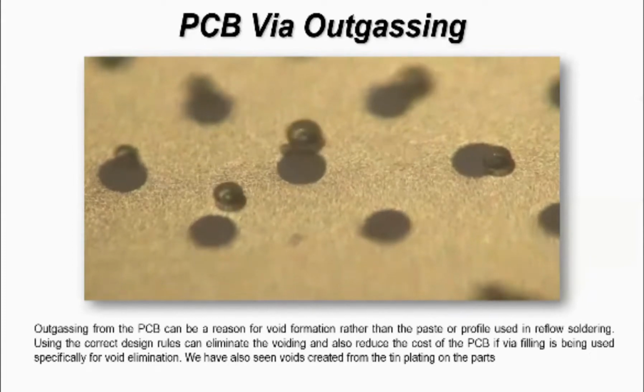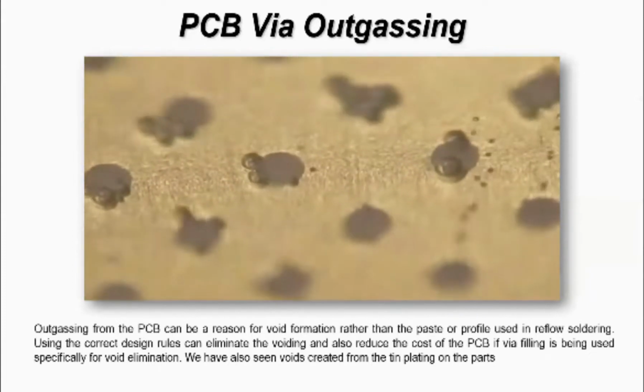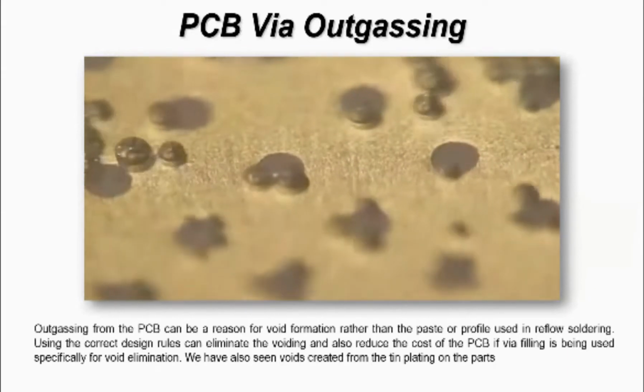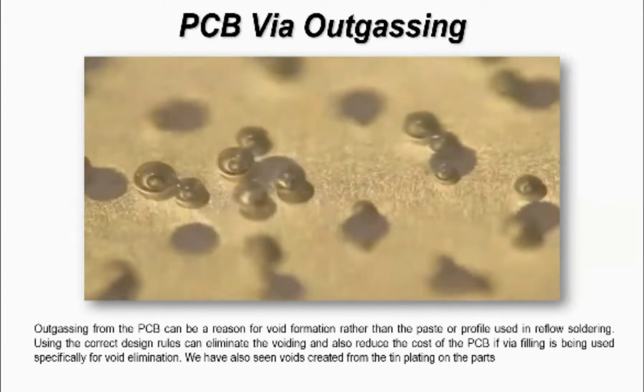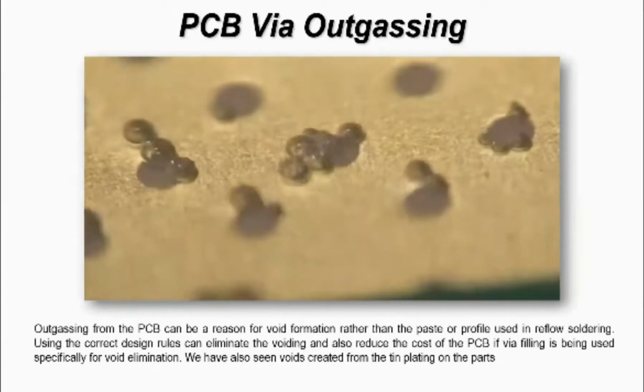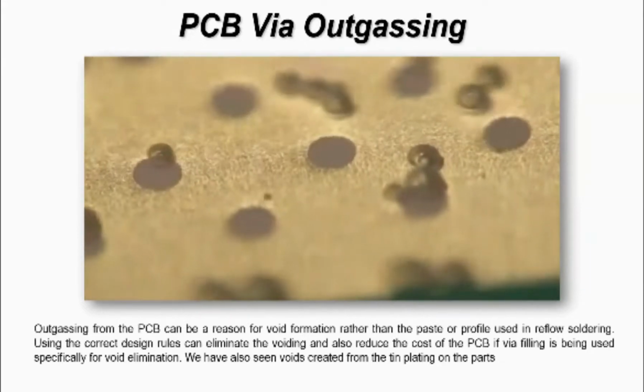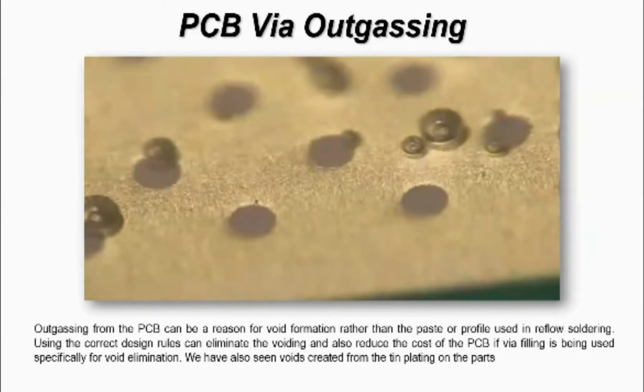Now back to what causes voids. You all know the long list of things that we evaluate, but here's a classic example of a board outgassing. And this is a board from that center pad outgassing, and these vias have actually been filled with an epoxy. So the vias have been filled with epoxy to enhance the reliability and improve the performance of this particular package. But what it did was actually create even more voids. And this is something that I demonstrated just with my simple oil test. Some of you will be familiar with the oil test for outgassing from PCBs. This is just on the surface of the board where we've got a flat surface and we're looking for volatile material coming out of the plating or, in this particular case, between the plating and the vias. And this would certainly, as it did, create voids